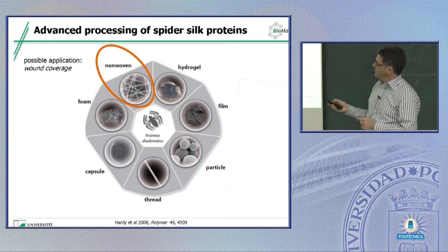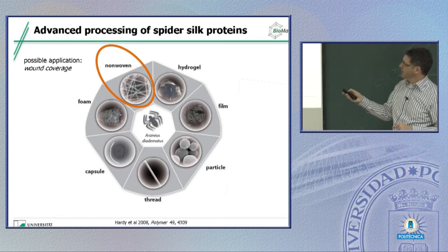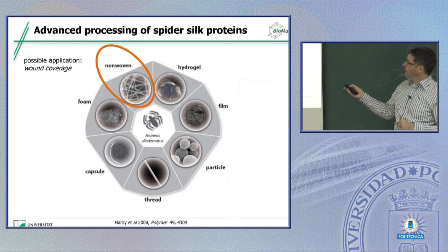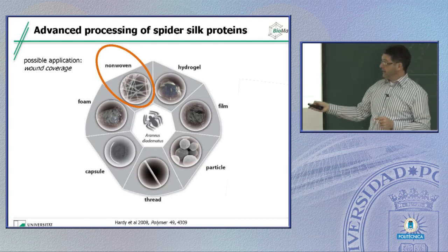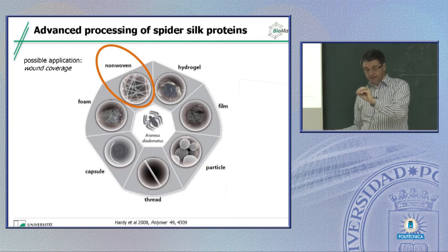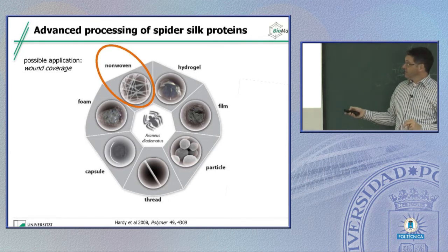And here you see the experiments with RGE sequences, either chemically coupled or genetically incorporated in the sequence, and both show the same results as in the absence of this sequence. Spherical cells, they make these aggregates, they lift off again. So this makes us very confident that what we see here, the cell binding, is highly specific to the sequence RGD, and it's highly specific to the structure.